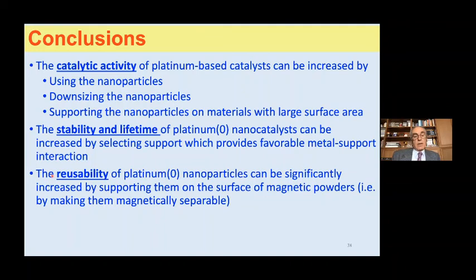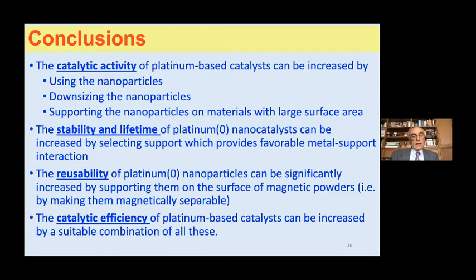The reusability of platinum nanoparticles can be significantly increased by supporting them on the surface of magnetic powders, by making them magnetically separable. That is the most important result which we have. Catalytic efficiency in general of platinum-based catalysts can be increased by a suitable combination of all of these approaches. So we should not rely only on one, rather we should combine them to get high catalytic efficiency.